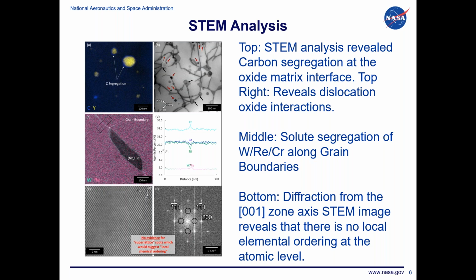One is, there does appear to be some carbon segregation between the oxide particle and the gamma matrix. You can see it here in this TEM. So this is high resolution, so 100 nanometers. We also see grain boundary segregation of tungsten and rhenium. So these are heavy solute elements, and we think that helps with grain boundary strengthening beyond just the carbides that you can also see here in niobium titanium carbide. So we think those two together are helping to strengthen our grain boundaries at elevated temperature.